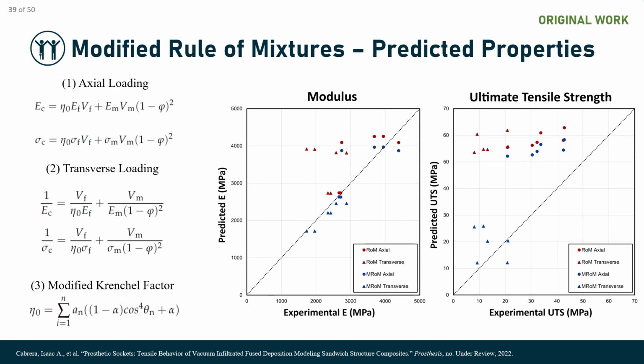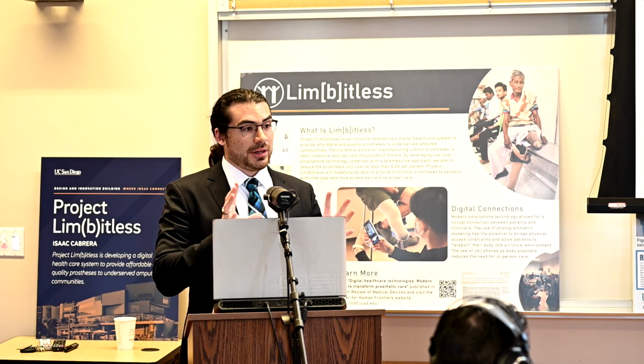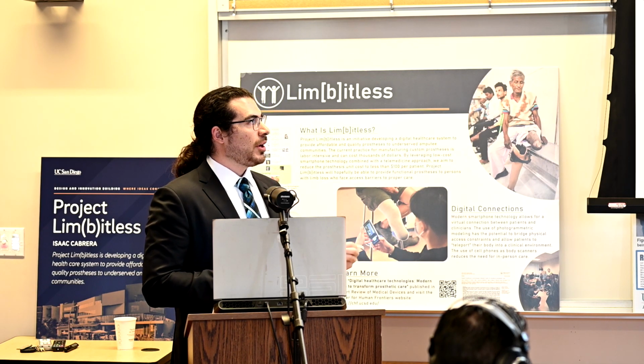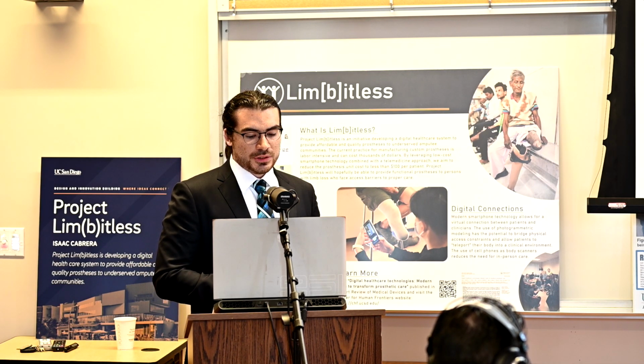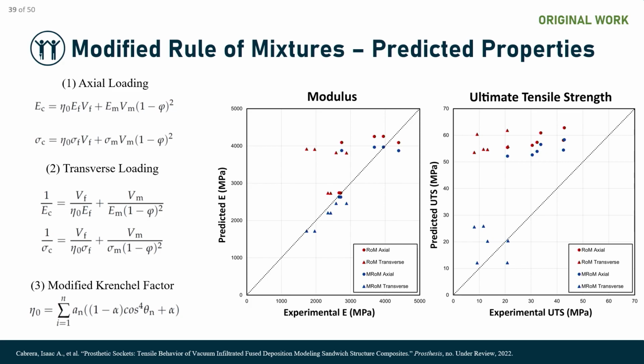Of course, this is a first order approximation, but adding these two correction factors really allowed me to more precisely predict the properties, specifically with regard to stiffness and not so much strength. What we see here on these graphs, the middle graph is our graph of our modulus. All the points that are red, I apologize, the audience can't see it as well, the projector is a little bit dark, are the ones on the very top. You can see that's quite far from that line of best fit for your model. And incorporating our two factors in, we're able to improve the prediction. So now, what are these two factors?